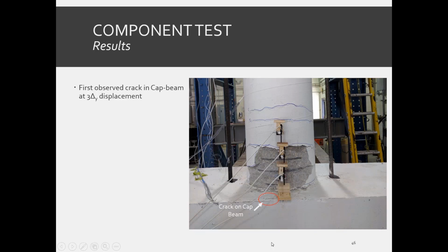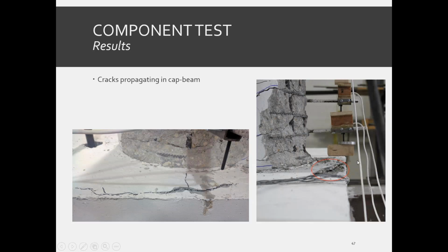No cracking was observed in the cap beam until the 3 delta Y displacement level. However, you can see that a crack initiated on the cap beam. The crack which I showed you in the last slide started to propagate at later stages of the test. Although this was superficial damage, we believe that better construction practices at larger scale will prevent such damage. Also, Caltrans provision suggests the bent cap width to be at least 2 feet wider than the column diameter, which means 12 inches on each side of the column to the cap beam edge. Since this parameter was scaled down to 4 inches on each side, it is believed that this might be the reason for damage on the cap beam.